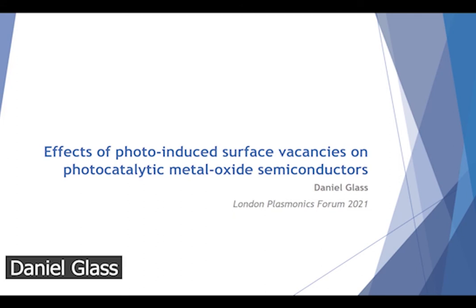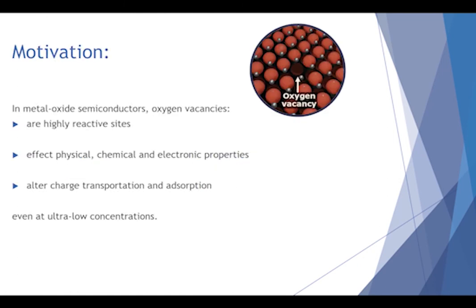Hi, my name is Daniel Glass, and I'm going to briefly tell you about my poster, which is on the effects of photo-induced surface vacancies on photocatalytic metal oxide semiconductors. Oxygen vacancies are some of the most reactive sites on metal oxide semiconductor surfaces. They can drastically affect the physical, chemical, and electronic properties of your film. For example, they can change the color, the reactivity, and also the band structure by inducing defect states. As a result, inducing oxygen vacancies on your material can drastically affect the charge transportation and the adsorption of molecules, the interaction of molecules with your surface.